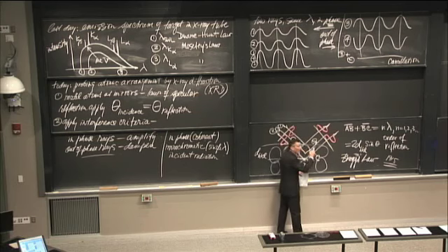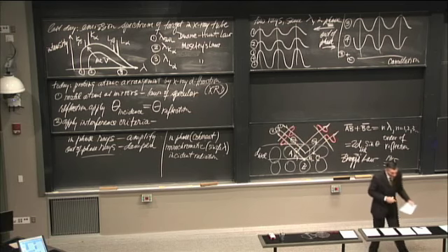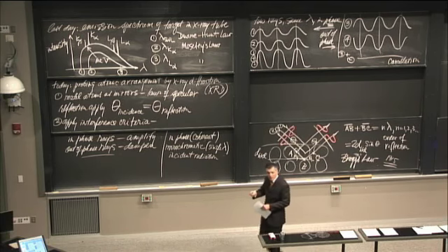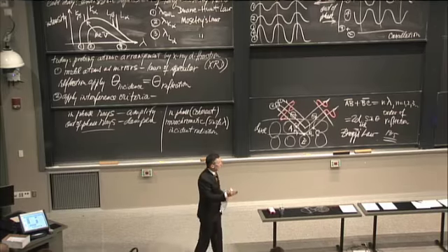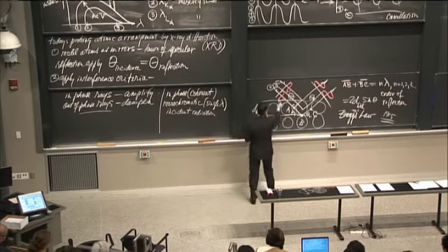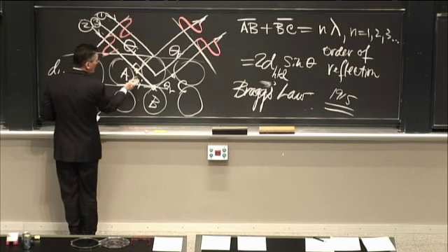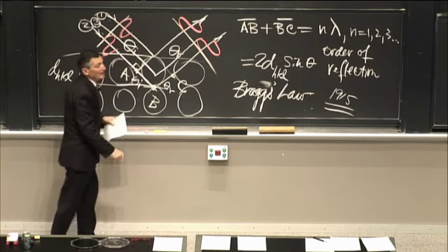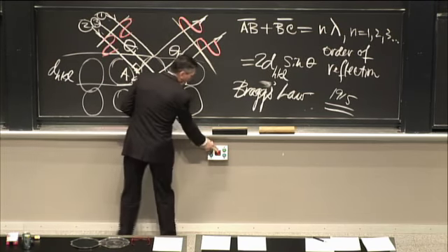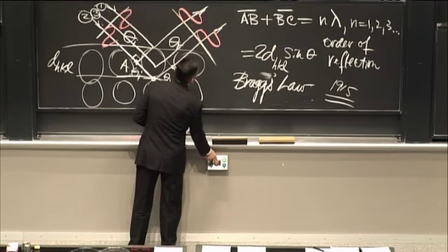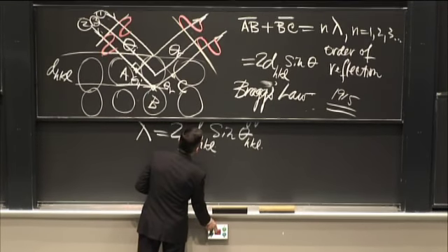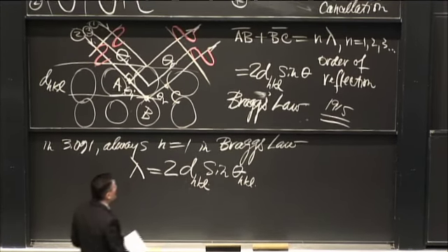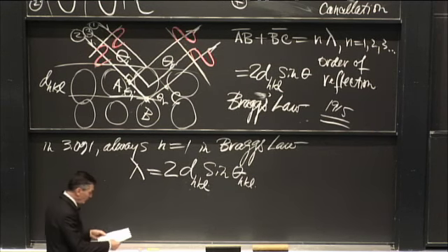And so by going through the set of crystal structures and recognizing that when you have a half wavelength difference, you get destructive interference, and therefore you will see no line. The incident radiation will come in at this angle, and at the reflection angle for that particular plane, there will be nothing detected. So you can see that you have a combination of selection rules that involve both the rules of interference and interaction with the crystal structure.